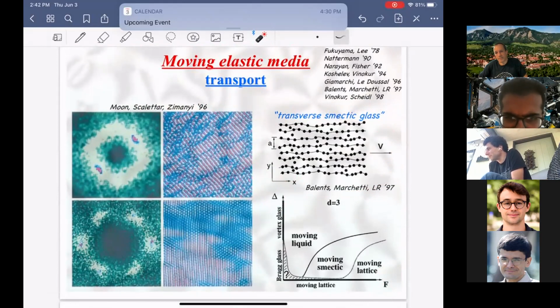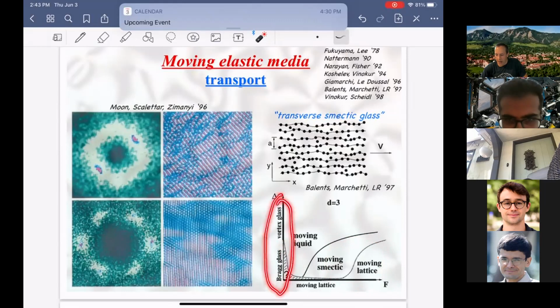Okay, so is it at low velocities that you have bigger symmetry, because you have a liquid while you keep reducing it? Well, this is kind of questionable. We don't know how to deal with this. We only understand it at high force or high velocity. The first observation is everything I talked about up to this slide, up to dynamics. Here's the Bragg glass, here's the vortex glass, and here's the phase transition right on this equilibrium line, F equals 0.